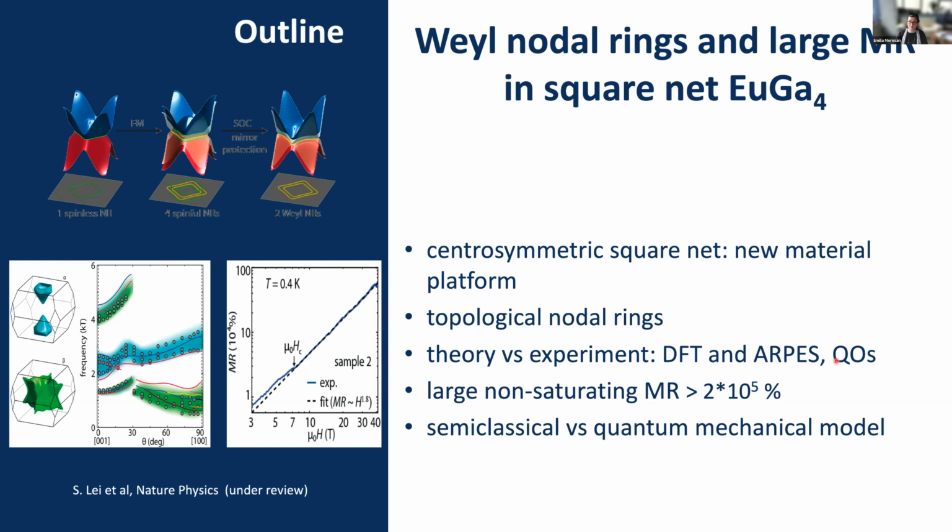In addition, we have quantum oscillation data that is also in agreement with all of these data and experiments. More importantly, one of the things that I've alluded to already is that we also see large non-saturating magnetoresistance in excess of 10^5 percent at high field, as I'm going to show you in a little bit.